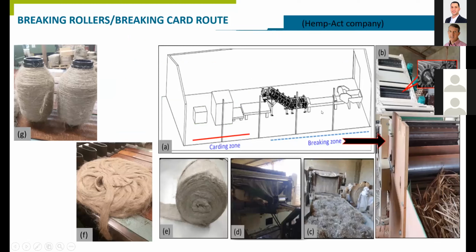We used for this approach breaking rollers and breaking card machines in collaboration with the Hemp-Act company, which is in the southwest of France. So this company has a device with successive breaking rollers, as you can see on these diagrams, and you can see the actual machine on the right. So in there, it's possible to introduce randomly aligned stems. I just want to say that it's important that the stems still need to be retted. And then after breaking, some fibers like this, which are again randomly aligned, can be obtained. There is still a little bit of sheath remaining.